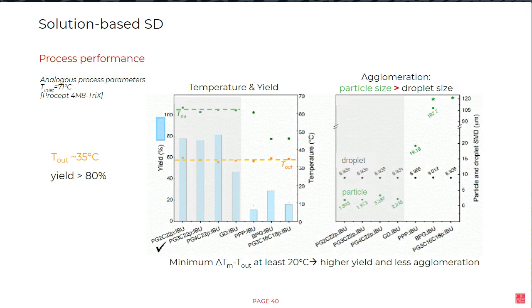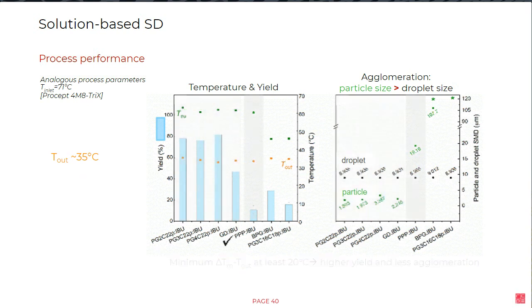Unfortunately, as you can see here, this is not applicable for all lipids. Considering the difference between outlet and melting is unfortunately not enough for all types of lipids. In this case, for tripalmitin, we are seeing exactly the same thermal conditions. The difference between outlet and melting is the same. However, the yield is extremely low, even below 10%, and there is agglomeration in the system. So consideration of the outlet is not enough for some lipid systems.